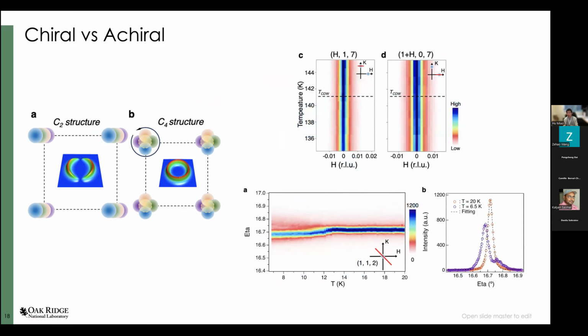So we did very careful Bragg peak measurements at the 90-degree related fundamental Bragg peaks, through the transition. Based on our experimental resolution, you can estimate the upper limit of the lattice displacement, which is less than 2 picometers. And if you calculate the Heisenberg uncertainty principle for the lattice vibration, it's about 3 picometers. So what I'm saying here is basically that the splitting already makes no sense at this temperature. Therefore, we believe at this temperature there's no four-fold symmetry breaking.